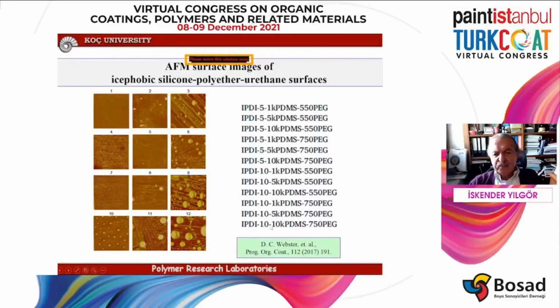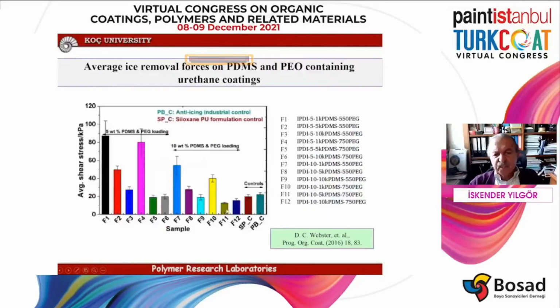And here they have shown that when you have 10,000 PDMS with 750 PEG, you may go all the way down to, again, around 15 or so. This F11 was the best one. And here F11 has 10% 5,000 PDMS and 10% PEG 750. So as you can see, and the last two are commercial formulations.